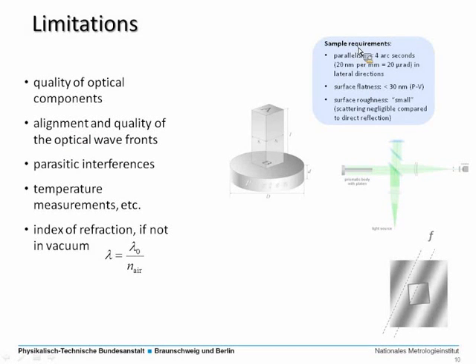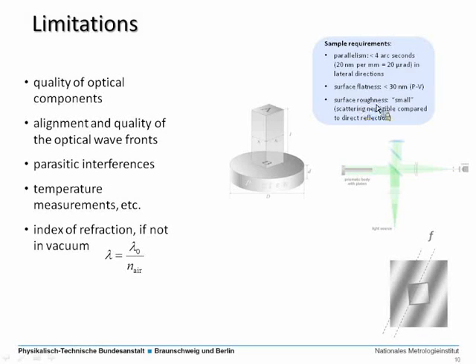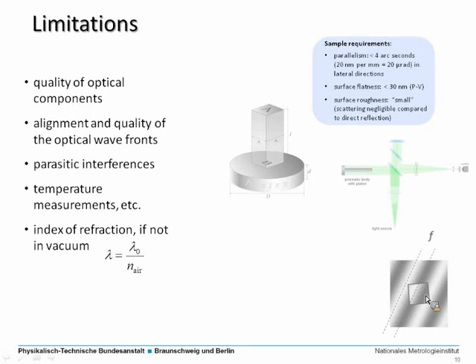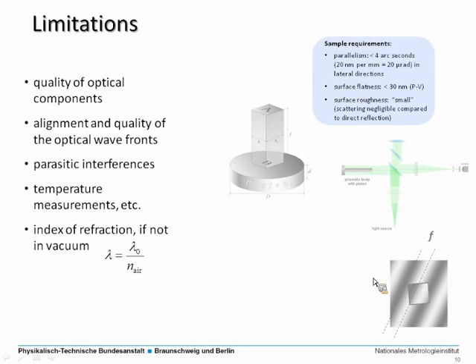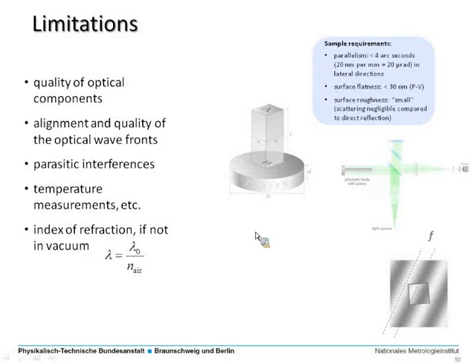And this is directly connected to the sample requirements, because if you have a sample which is not very parallel regarding the front and the back side of the sample, you would have a tilted fringe pattern, and this tilt is a systematic influence on the measurement result if it's too large. Also, surface flatness is important, and of course roughness, because you need a reflective surface in order to perform this optical measurement.